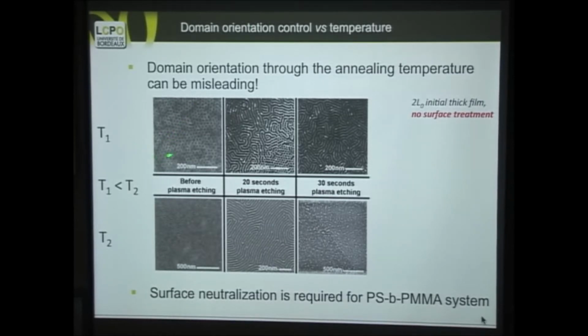But eventually when you etch the first layer, you see that the cylinders in the middle of the layer are lying down, and farther on they lie down. So if you use a temperature higher than T1, then you see that all the cylinders are lying parallel to the substrate. So here with the temperature, we don't have good control.